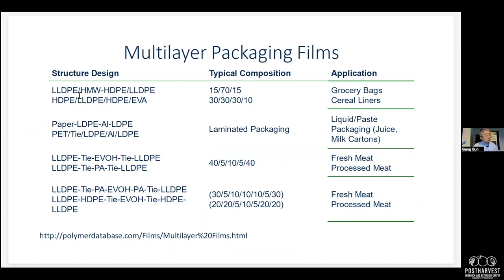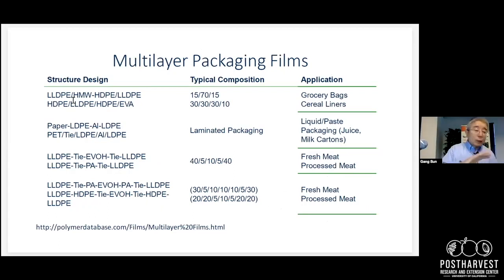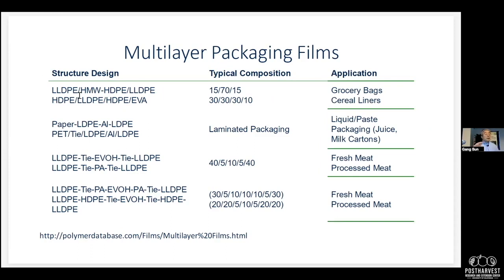So you have an LDPE and HDPE, LDPE multi-layer. The HDPE provides the strength, and the LDPE provides the stretchability, but they are the same thing, so they have good self-adhesion functions. And there are others. If they don't have good self-adhesion functions, nowadays the industry has a very quick so-called plasma treatment, and for multi-layer, on one surface or two surfaces, they can increase the adhesion. So natural adhesive function, which in the old days was very important, nowadays becomes less important. They do have one quick process, plasma treatment, to improve all the adhesive functions.